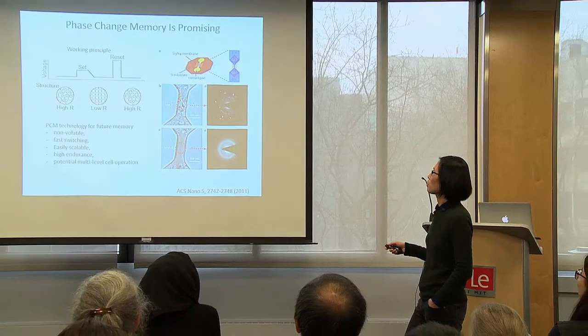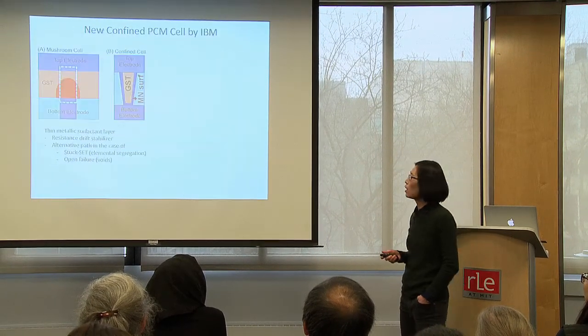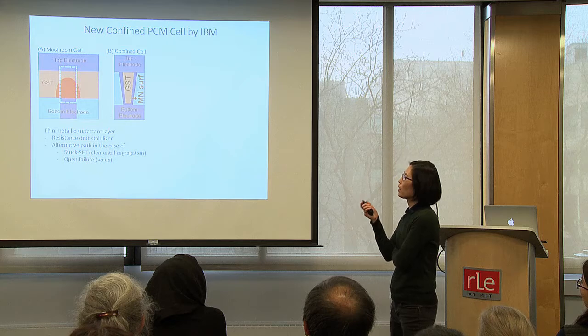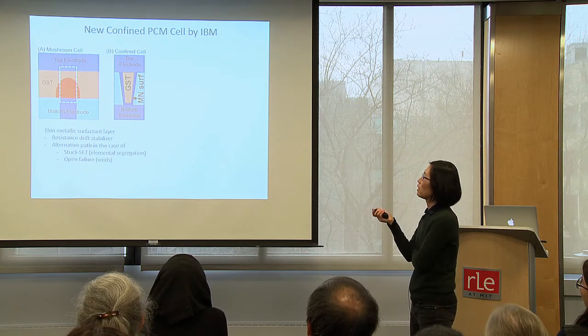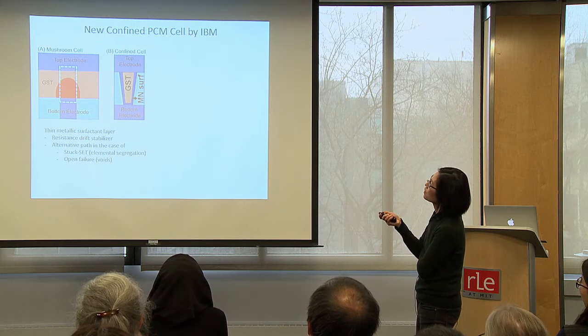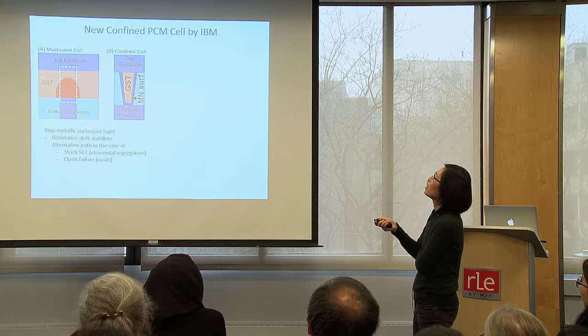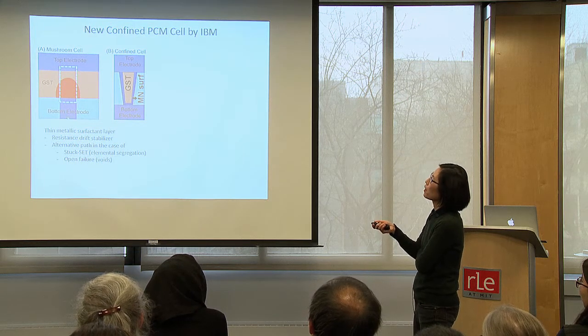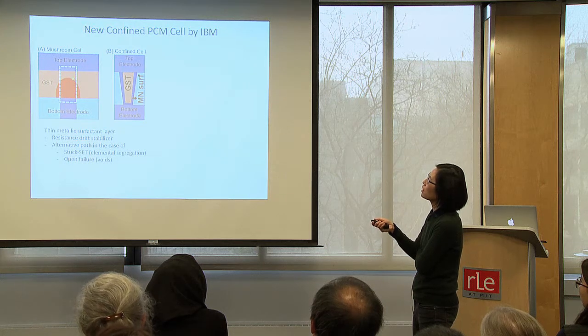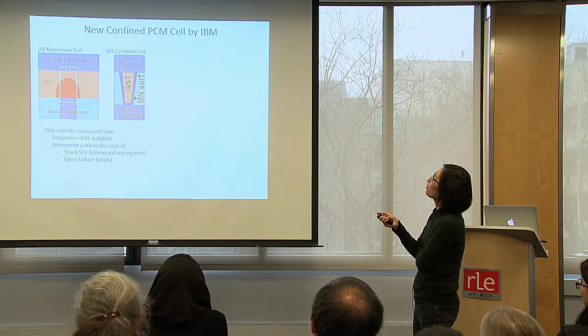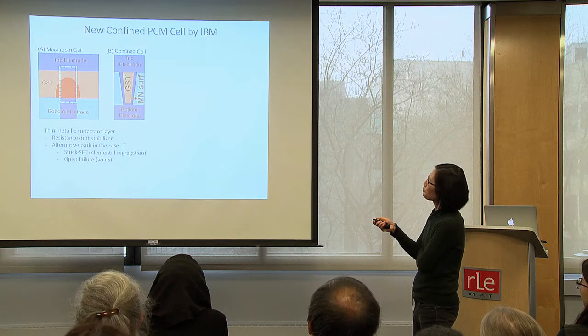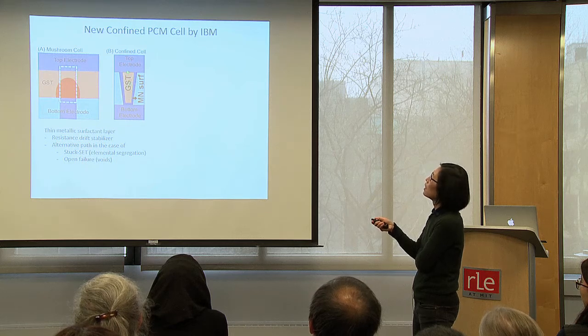Okay, when I was at Stanford as a postdoc, many years ago, we made some academic version of PCM, just thin film, sputtered film, and showed, yeah, we can do this in situ. When I moved to Yale, we started working with IBM on their next generation confined PCM cell. This is the conventional mushroom cell you can buy, right? Here's your GST thin film. You have a bottom electrode that just locally changes the phase of the GST. The new one that IBM made is a plug. They've developed processes to fill this plug very reliably and densely.